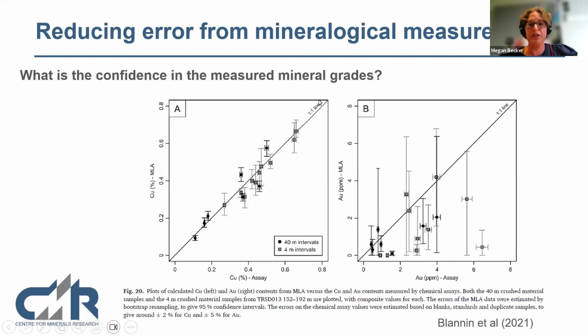So for something like copper, where we're dealing with absolute numbers like 0.2 to 0.6%, you can see the error bars are quite small. Here they did gold, and now we've gone into ppm, and you see the size of the error bars. That has got to do with the fact that because gold is a precious commodity, there's just so much less of it. So for us to get more confidence, we have to analyze so much more material to get confidence in that measurement. And so this is why with something like analyzing concentrates, we can get really good confidence in the measured grades, but give us a tails, well, we struggle to find particles. And the confidence in the data is obviously less because we've measured fewer particles.